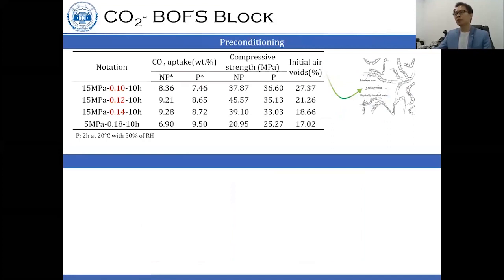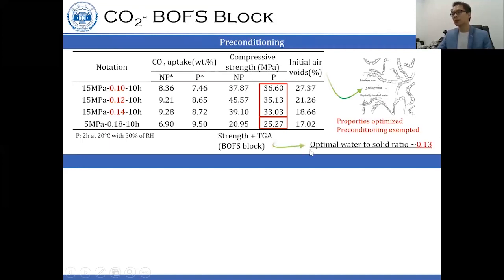So the preconditioning is a very important parameter that we have to consider, whether we need to remove some of the excessive water before we run the CO2 curing. So we have selected 4 different samples with different water to solid ratio, and we found that, this is preconditioning, this is non-preconditioning. So we preconditioned for 2 hours at 20 degrees C with RH of 50%. So we found that after the preconditioning, for the low water to solid ratio, it decreases the reactivity, CO2 uptake, as well as the strength. However, for the high water to solid ratio, the preconditioning actually could help to increase the strength by 20%. So we can conclude that if we do not have an optimum water to solid ratio, we can extend the preconditioning.